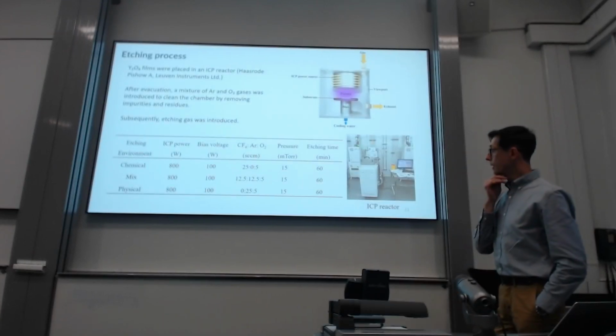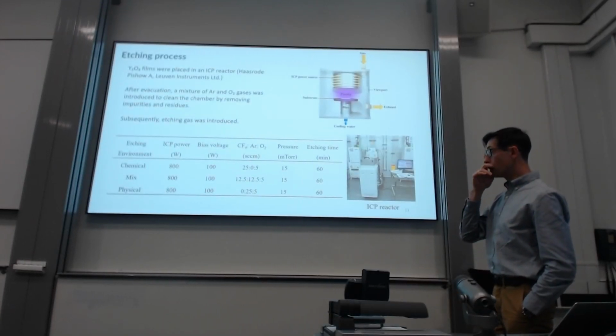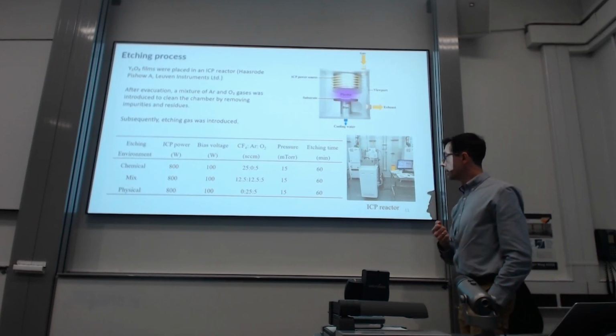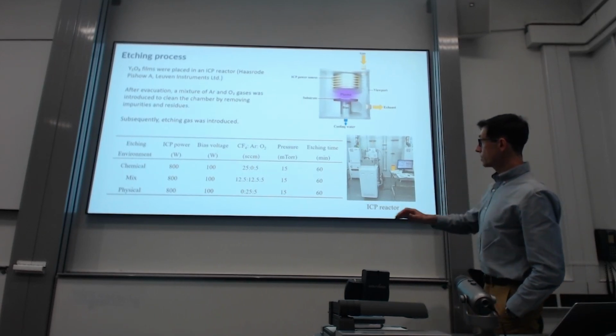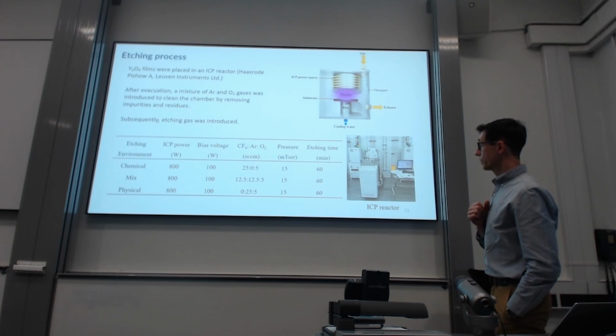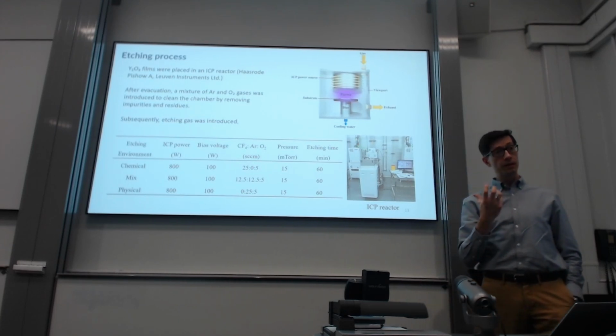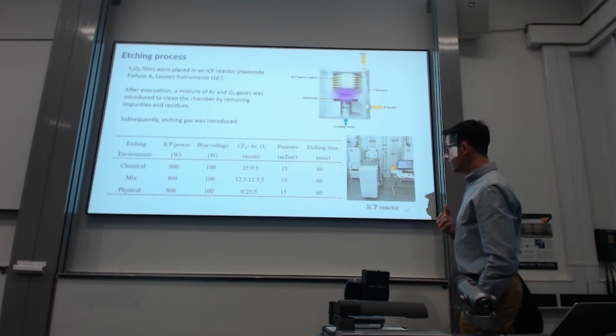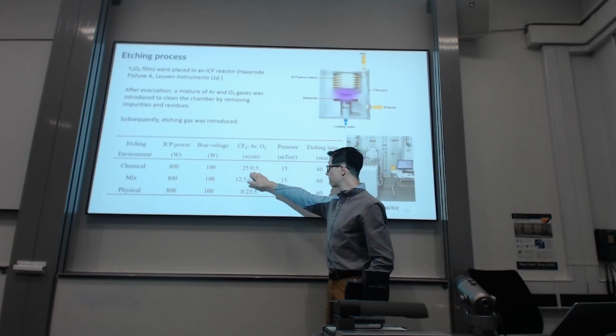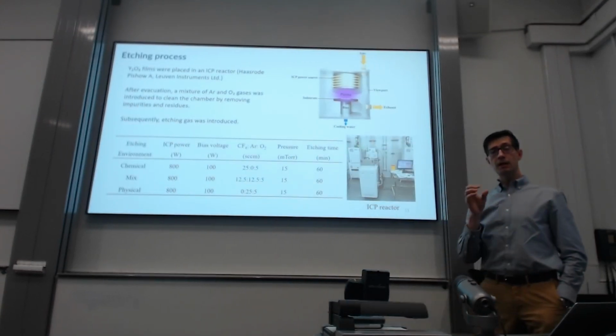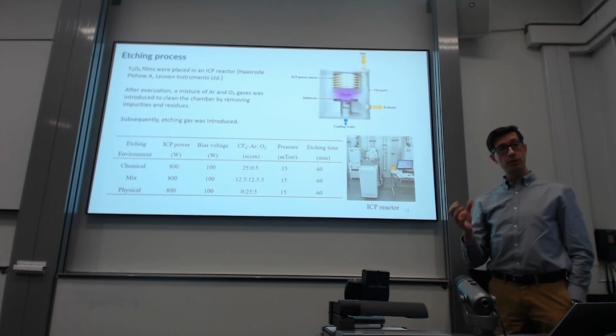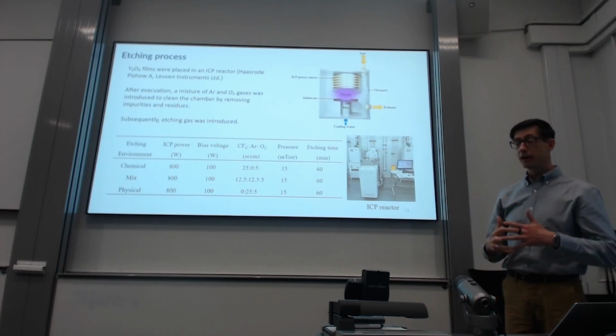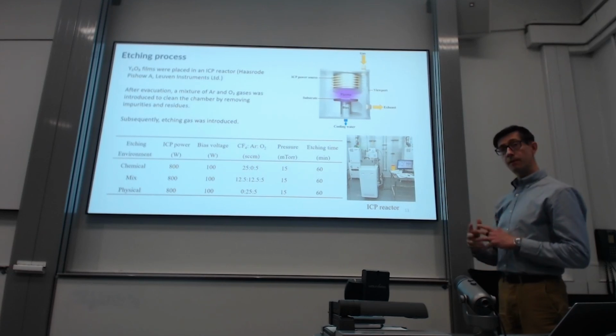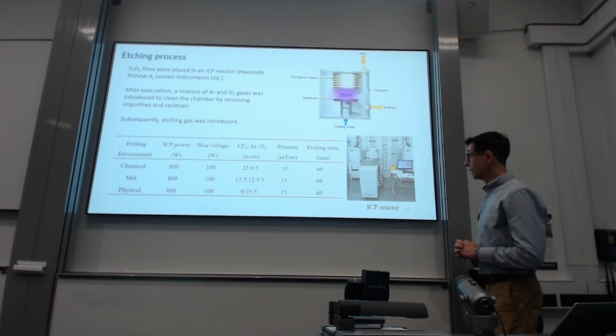So let me spend just a minute on explaining what we mean by chemical and physical etching. So in terms of the three variants for etching, you have the same ICP power, bias voltage, pressure, and etching time. So the only variable is the gas environment in the chamber. What we mean by chemical etching is that we don't have argon at all in the chamber. So we don't have argon bombardment of the surface. So we don't have that, let's call it, physical interaction between the plasma and the surface.